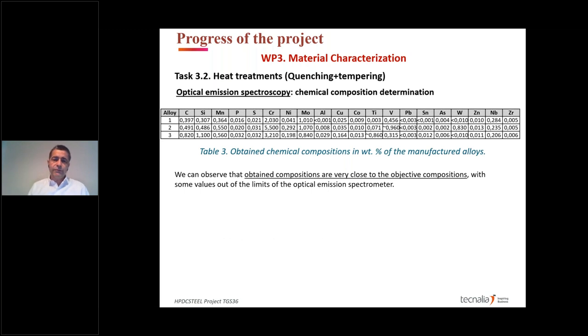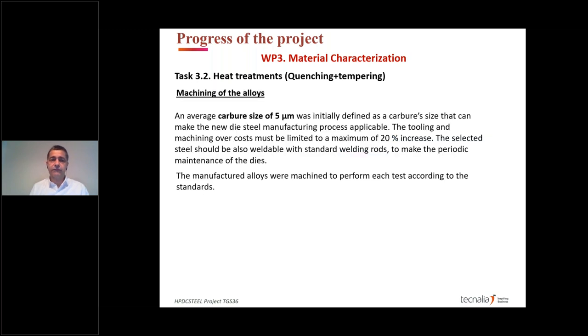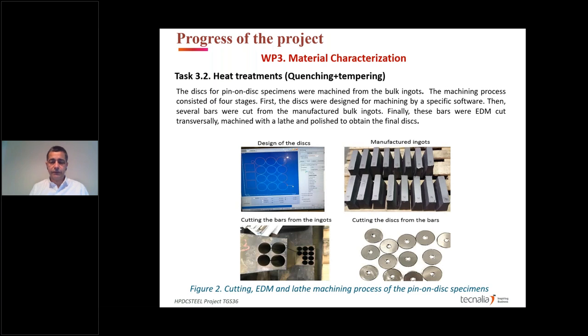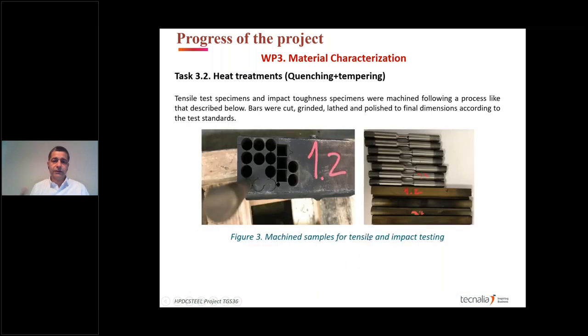So we produce in the laboratory tests, we make the chemical compositions, and we observe that the obtained compositions were very similar to the ones that we wanted. So also for the machining, we wanted to have less than 5 microns in the carbide size, and with the selected steel a maximum of 20% increase in the cost. So here we make some different trials of machining, including electrode discharge machining, milling, and lathing, obtaining different prototypes and parts.